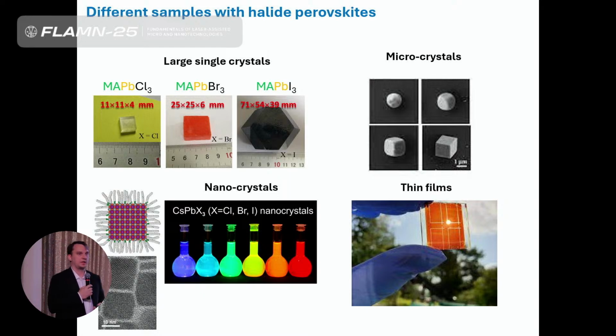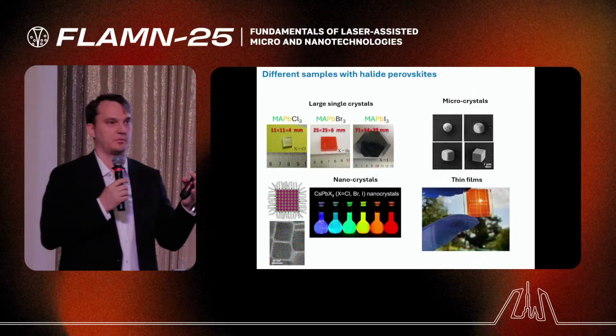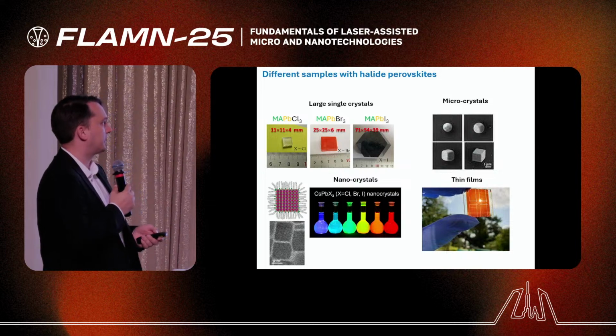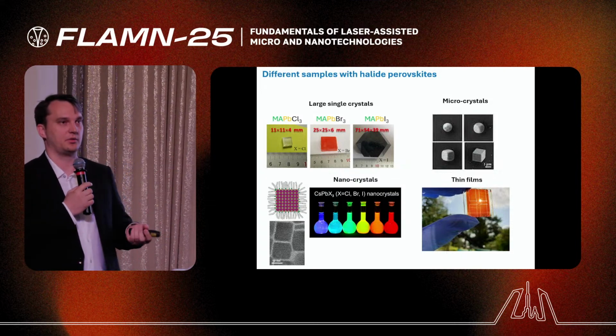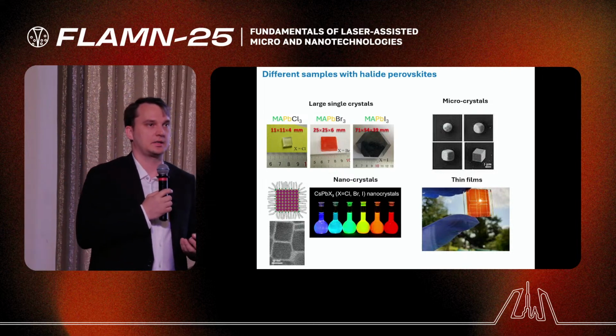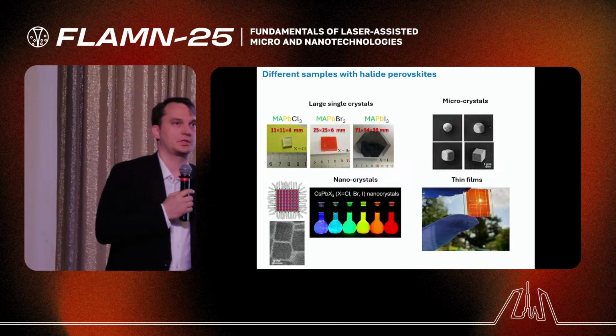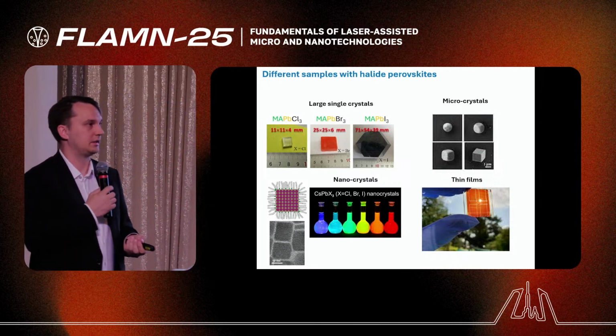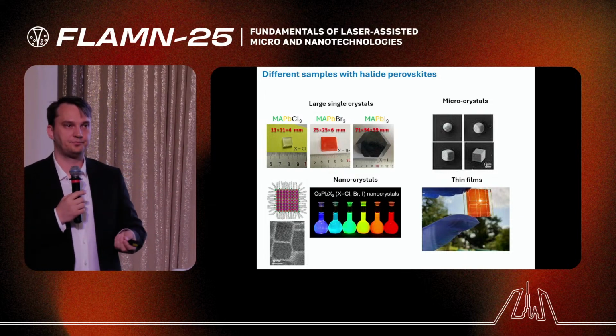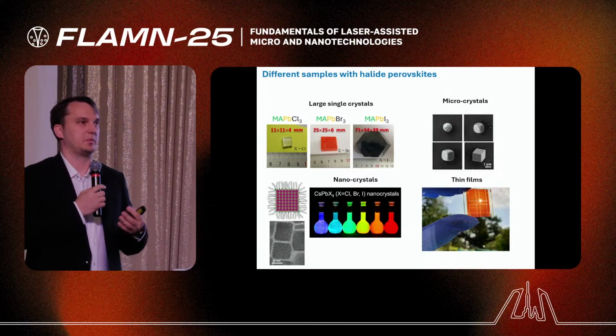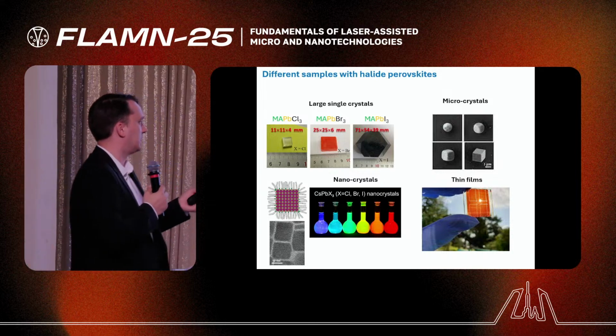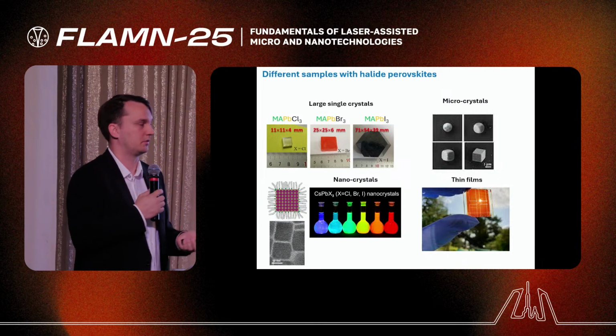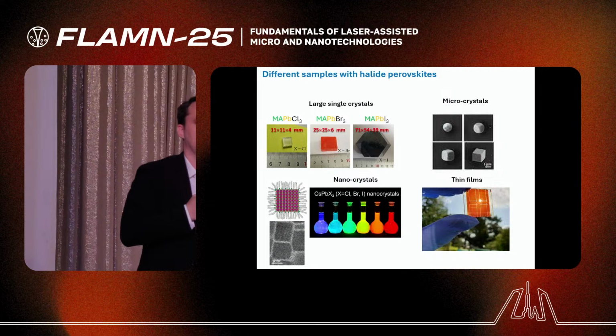And what kind of samples can we create made of perovskites? Of course, we can create large scale, centimeter scale macrocrystals, and also microcrystals. You see that the scale is around 1 micrometer or less. We like such objects when we apply them in nanophotonics and nanolasers. But nanocrystals is also a huge family, a big direction now, because they can be deposited easily on arbitrary surfaces and emit light very efficiently. The quantum yield of these nanocrystals is very high, more than 90%.